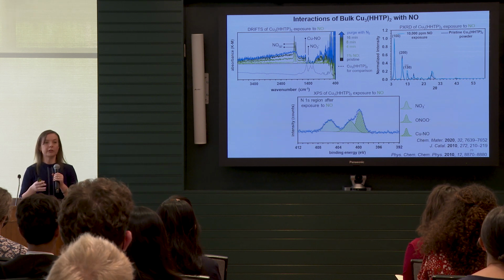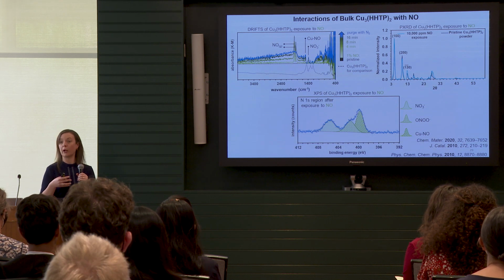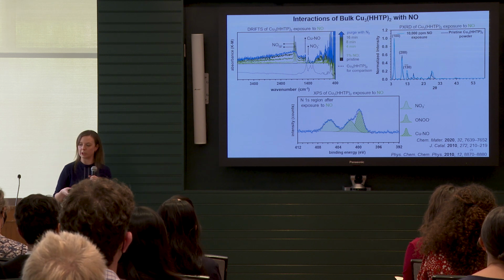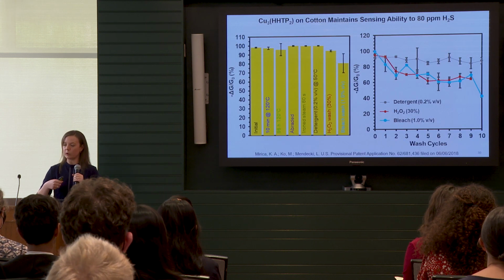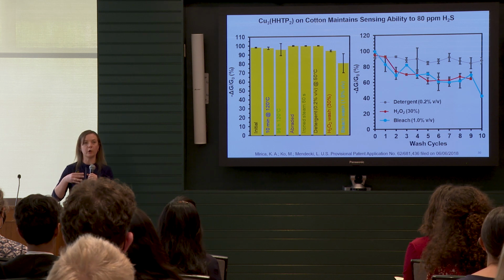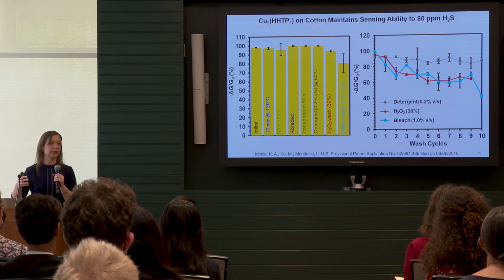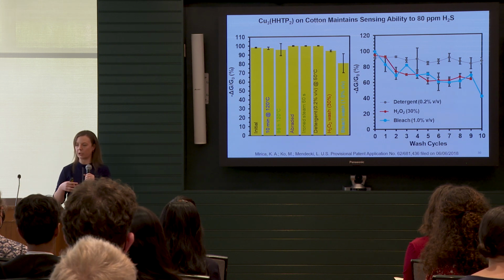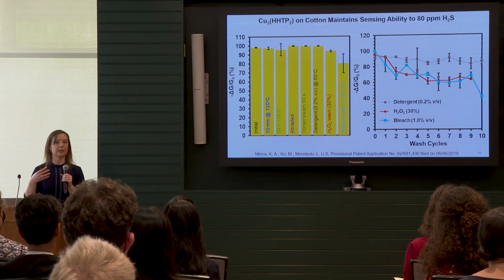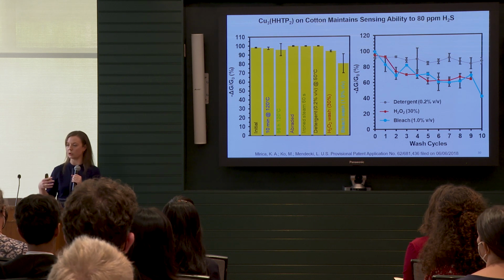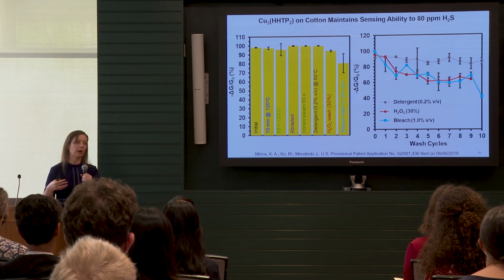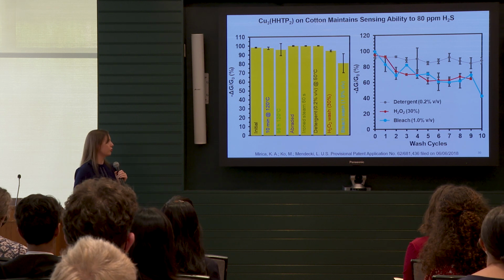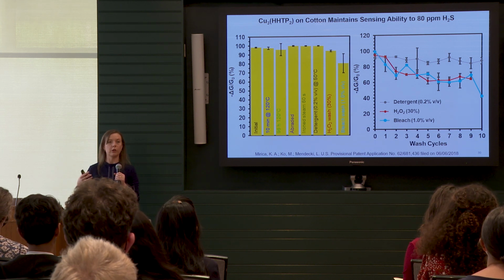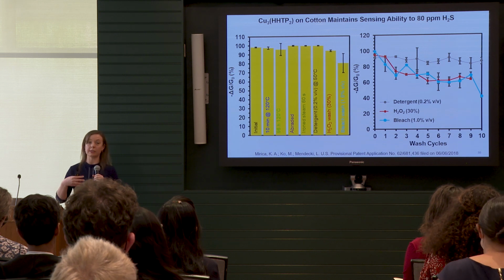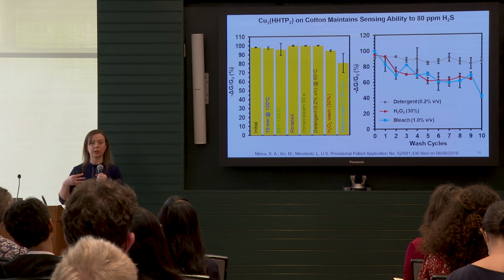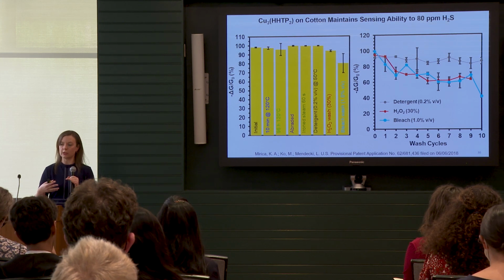And we can completely restore the framework material by washing it after it's exposed to these analytes. And not only can we restore it, we can actually perform washing cycles and maintain sensing ability by washing this material with detergent, water, bleach, and the sensing ability holds up, although it does begin to decay after multiple bleach washes. This material is also extremely stable to heat and abrasion, so this combination of this particularly stable sensing material and the textile substrates together make this a really unique technology.